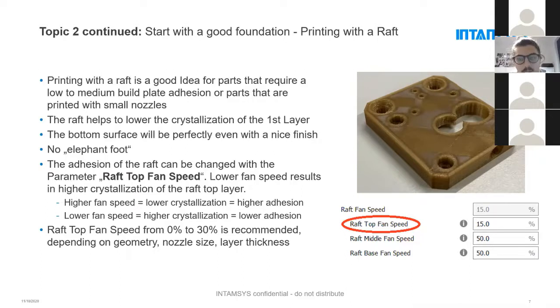The good thing here is when you print PEEK with a raft, you set the distance between the raft and the part to 0, which gives you a perfectly even surface on the first layer. You have no elephant foot, you have a good adhesion, and even on small nozzles where it's very hard to get a perfect build plate leveling, you have no issues within printing. You can play a little bit with the crystallization of the raft, which has a big influence on the adhesion between the raft and your part itself.